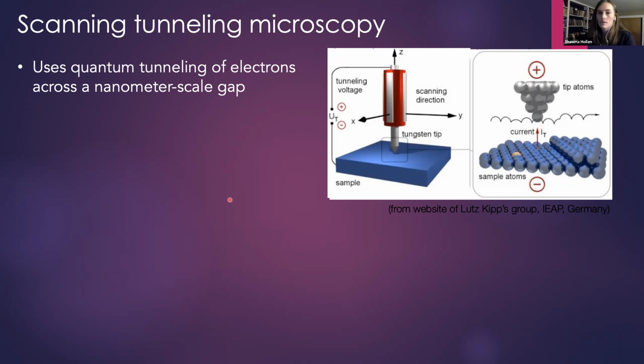So when it's that close to the surface, if you apply a voltage between the sample and the tip, so you put like a battery there, then there's some probability that electrons from your sample will tunnel into your tip. That means they aren't in the sample anymore and they appear in the tip. So this is quantum mechanical tunneling. It's a really cool phenomenon. All we can say about it is the probability of an electron making that tunneling transition. We can't say whether it will definitely happen or not. But if we make an attempt at it many, many times, then statistics are our friend, and we can turn probabilities into numbers. So we can measure a tunneling current of electrons over this gap.